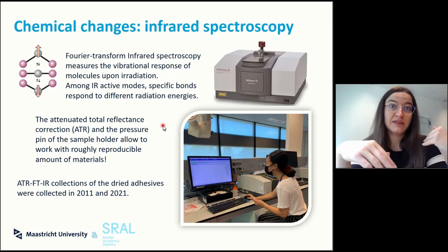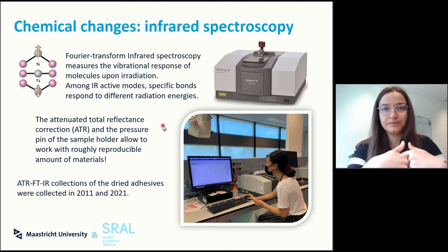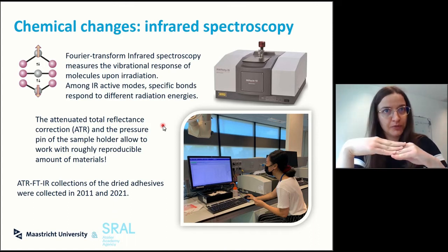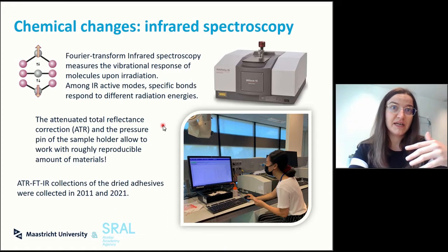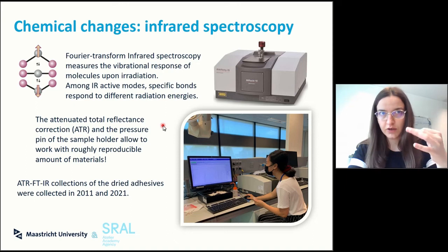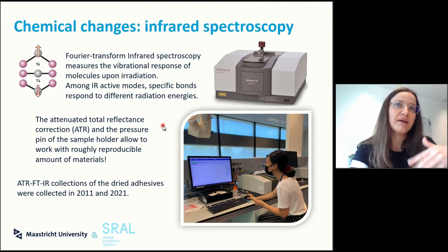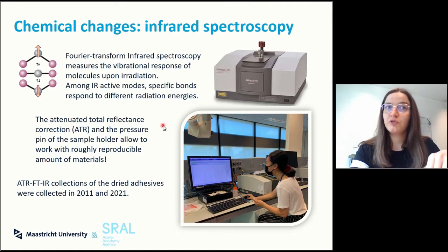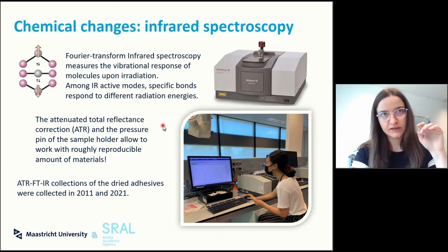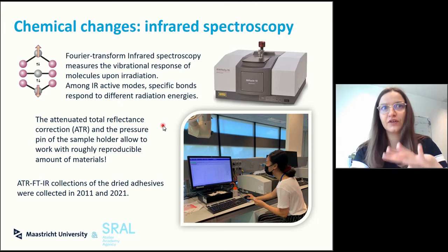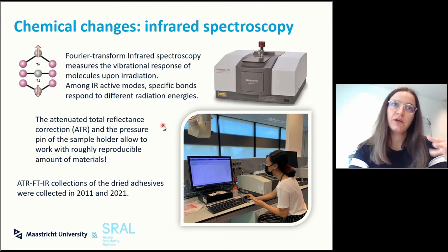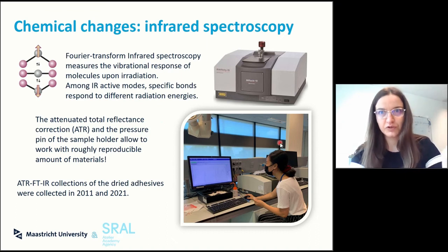We just scraped from the glass and from the brush out, and placed it on the IR pin. There is a pressure pin in the IR that fundamentally pushes down on the material. So if you are consistent in your placement on the spot for the sample holder, the pressure pin gives you a way to reproduce roughly the amount of material that you're measuring every time, even if you're not capable of precisely measuring, because we are talking about fractions of milligrams. An initial ATR FTIR was done in 2011. In 2021, we reproduced it at Maastricht University, so caveat that the first collection and the collection 10 years after was done on two different pieces of equipment with two different people, and kudos to the several undergraduate students of this group that took all of these measurements.